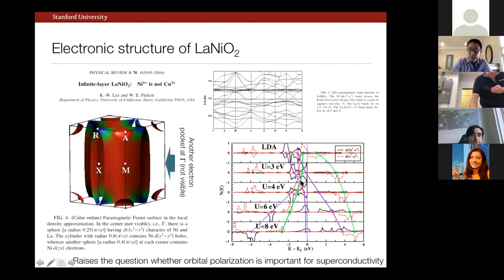And I just qualitatively wanted to trace through one thing, which is that this is the uncorrelated band structure. And as they increase these correlations on the nickel 3D site, what you can see here is that the x² - y² states, this cuprate-like hole band, splits to an upper and lower Hubbard band, as you might expect. But this additional feature of having these small electron pockets is quite qualitatively different, namely that you have also a splitting of these z²-like symmetry states, but you end up pinned in terms of having a Fermi surface, even up to very high interaction strengths at the Fermi surface.